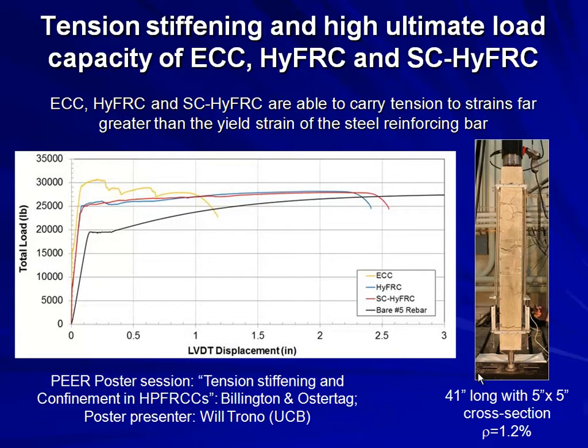So what you see in this case here, these are very large tensile specimens. They're reinforced, the reinforcing ratio 1.2% with a number 5 rebar, and we pull them in tension. And what you see right here, first you see this very nice tension stiffening effect. We tested the ECC, the hybrid and the self-consolidating hybrid. The yellow one is the ECC, and the other ones are the hybrid and self-consolidating hybrid. In all three cases, you can see the ductility there.